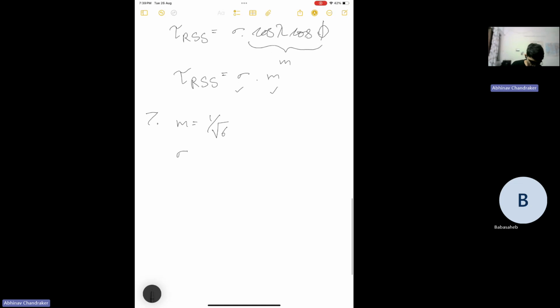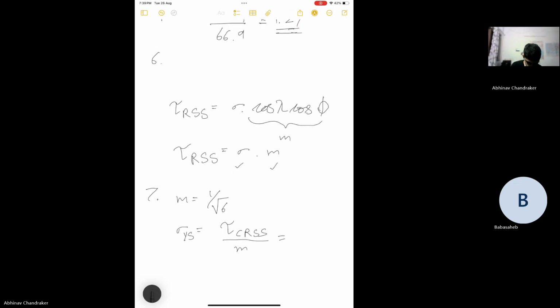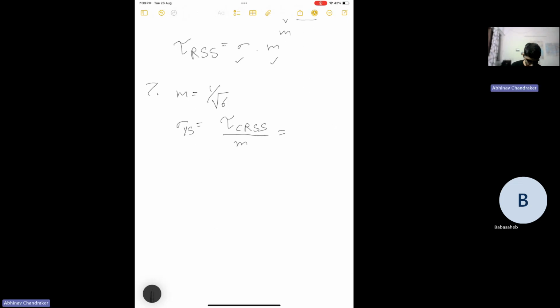And sigma is equal to tau CRSS. Yield strength will be tau CRSS by m. So this will be equal to 50 megapascal divided by 1 by root 6, which is 122.5 megapascal.